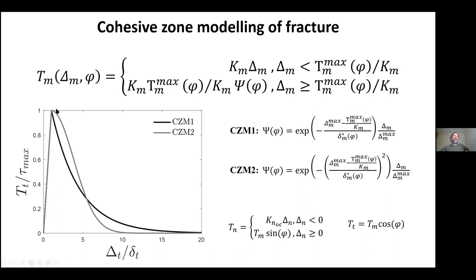First of all, what's the critical traction that will cause the fracture to initiate? And then what's the area under this curve? That's basically a measure of the amount of energy it takes to fracture the material. In other words, how much energy must be stored in the material before a crack will grow in an uncontrolled manner. Fracture is all about cracks getting into a regime where they grow in an uncontrolled manner. We've developed lots of cohesive zones, some of which we've applied to blood clots and in-stents. These cohesive zones involve definition of the maximum tractions and also the energy under the curve, the amount of energy it takes to perform a fracture.